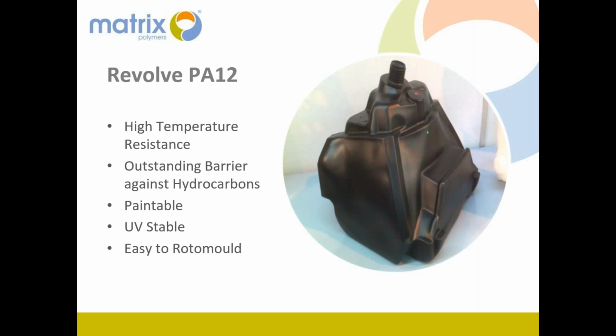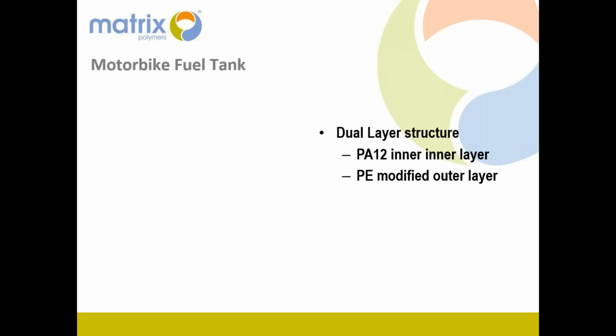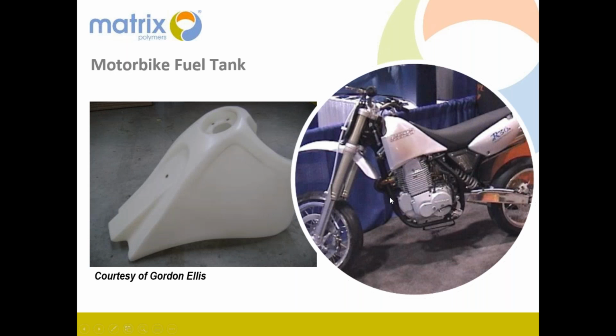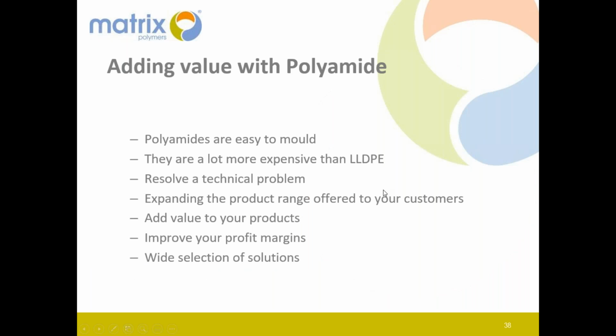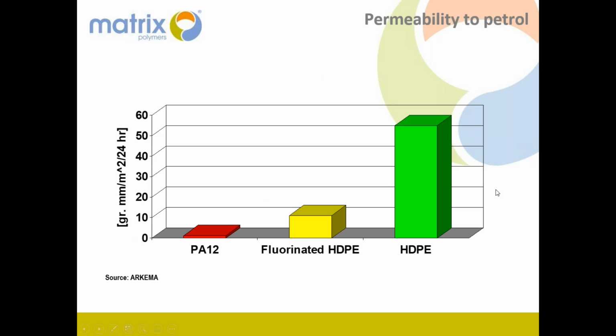High temperature, outstanding barrier, paintable, UV stable, easy to rotomold. So these are dual layer petrol, dual layer motorbike fuel tanks, as I indicated earlier. Nylon inside and cross-linked polyethylene outside. So polyamides are easy to mold. They're a lot more expensive than LLDPE. This slide seems to be a repetition, but this helps expand the range of products that you make if you can consider polyamide for certain applications.